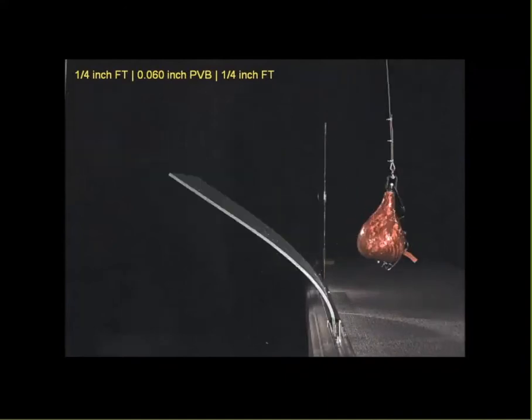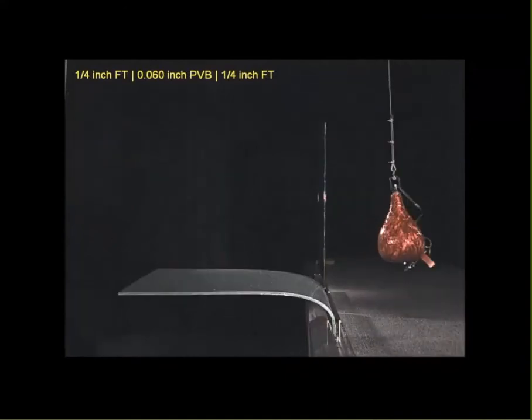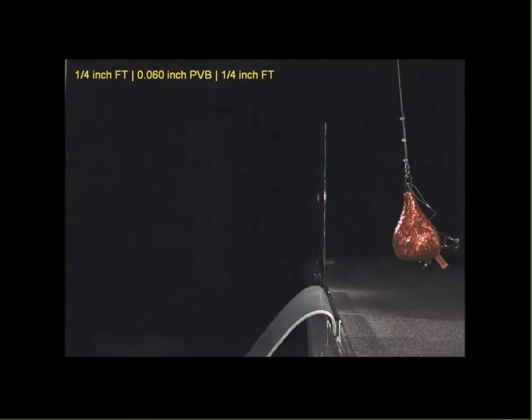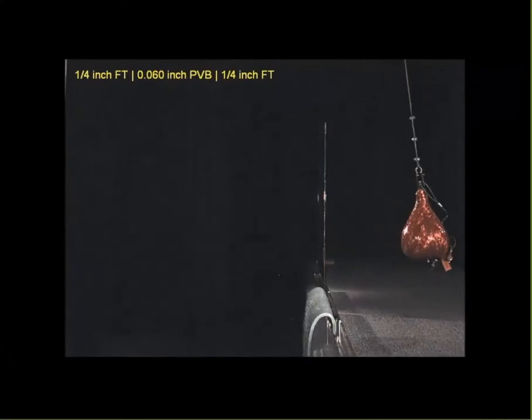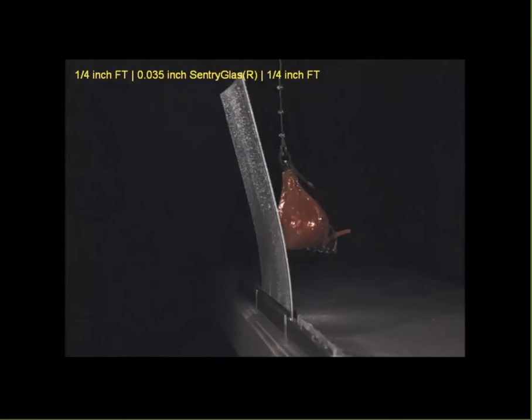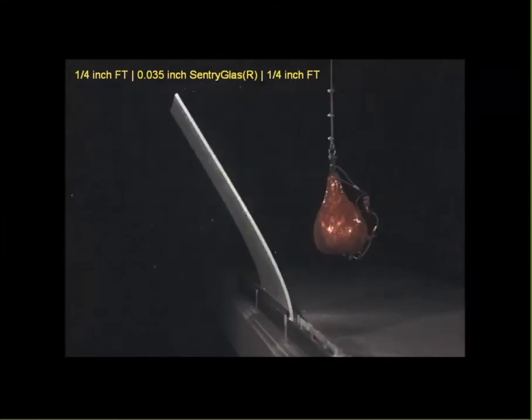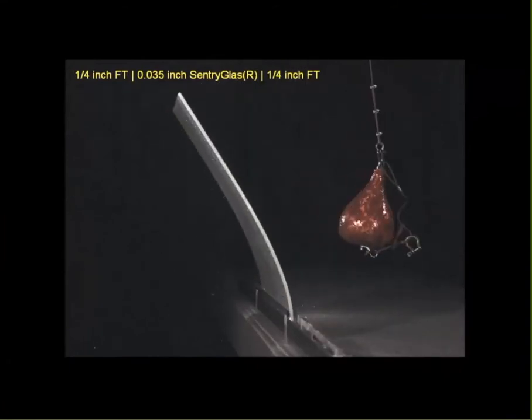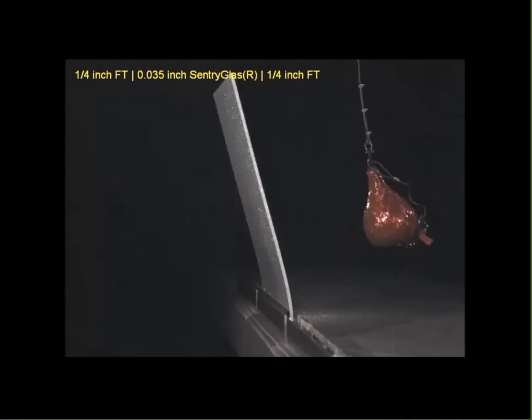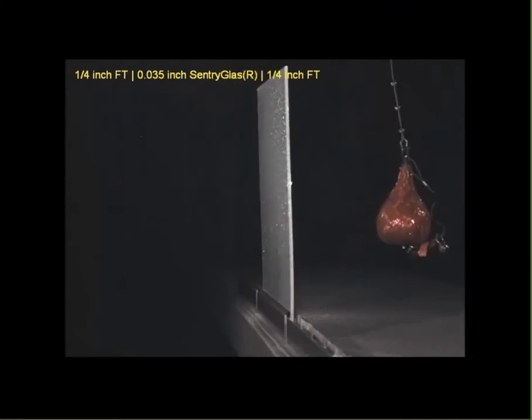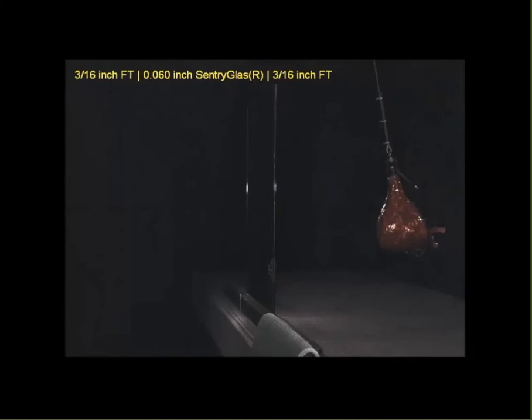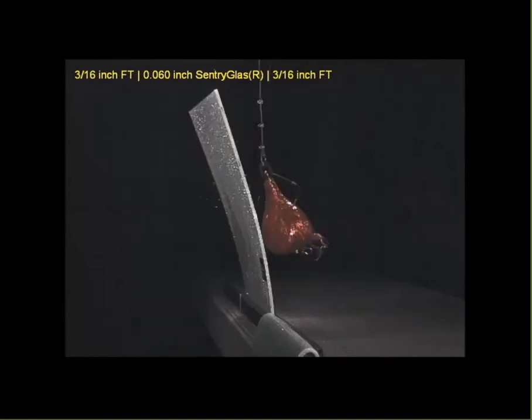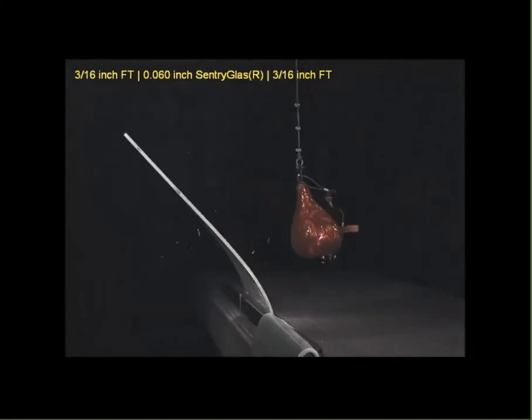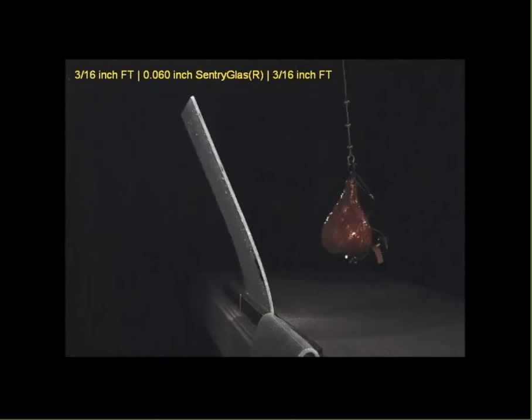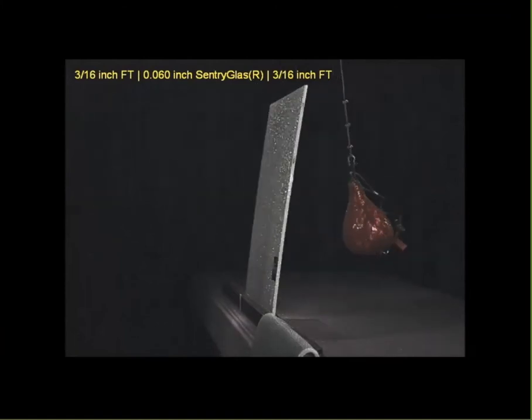PVB, this is very similar to what you saw earlier. Once the glass is broken, there's nothing there to reinforce the PVB and allow it to stand up. It falls over like a wet blanket. And now with the SentryGlass, and this is a thin SentryGlass, only 0.035 inch thick, it deflects and it stands up, and it provides protection not only for the people below, but it will provide protection for the people on the elevated surface.